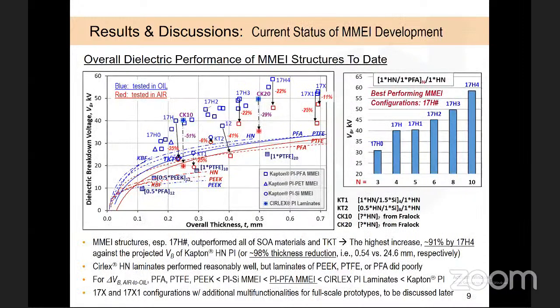The figure on the left is the master plot summarizing performance of MMEI structures to date in direct comparison with the SOA materials. Clearly, MMEI outperformed all of SOA materials regardless of test medium. The plot on the right shows the best performing MMEI configuration consisting of 1 mil thick HN and PFA, and its VB increases with increasing the repeat unit more than proportionally. To date, the highest increase was 91% from 17H4 sample compared to Kapton alone sample.